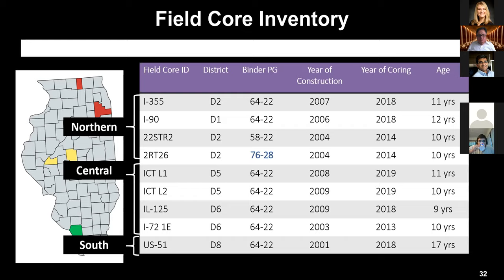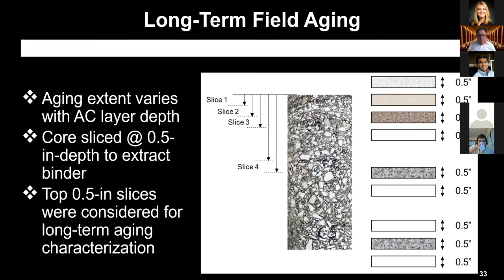The bulk of them were 64-22. You had one 58-22 and one 76-28. The ages ranged from 9 to 17 years. And you will see in the next slide that the aging extent varies with the AC layer depth. The cores were sliced at half inch depths and the binder extracted. The top half inch slices were considered the long-term field-aged samples and will be used for characterization in the next slides.